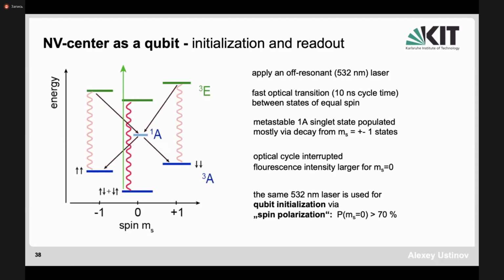And also there are some long-living metastable states, which are populated because of decay with the change of the spin number state. So the excitation of the system to the visible fluorescent state can be achieved by pumping with off-resonant lasers. So basically you pump with this very large energy, and then some small energy before you get to those states goes into the phonons and other excitations in the system. And then those states here are occupied, and then the fluorescence can be observed.